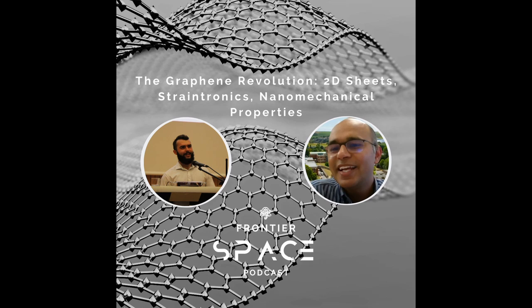No, it is really interesting, and that part of the research gave us a very good idea of Straintronics. When we were working on these textured surfaces, we found that graphene stretches differently on different textured surfaces. It's a single silicon wafer, and everything is the same, just different in the spacing. We found different strain in the graphene, and each strain acts differently. So we thought, oh wow, it's a typical field of Straintronics. The graphene is the same, but just the spacing between the texture changes its properties.